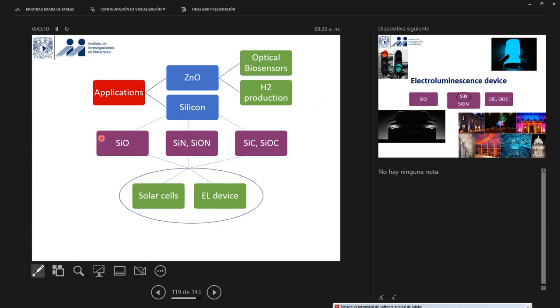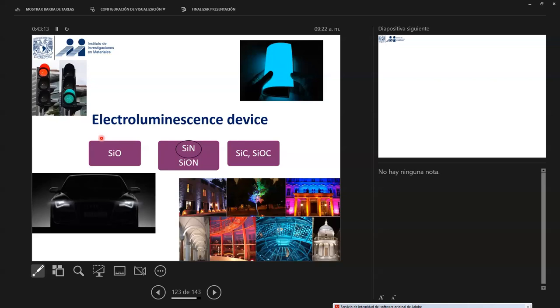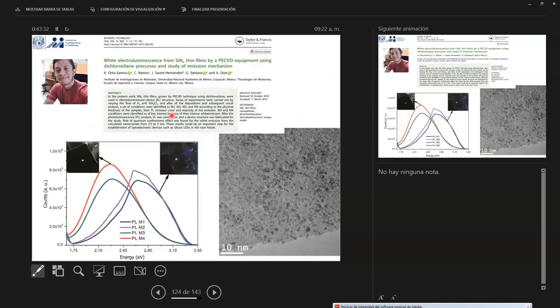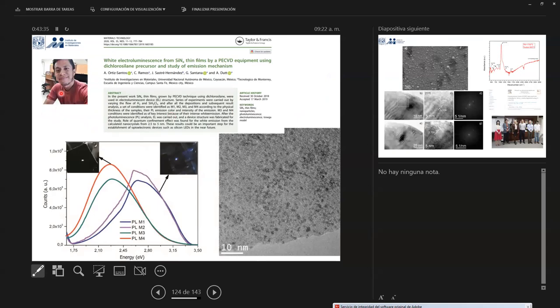Also, we are working on silicon structures. In this case, the aim is to use these silicon structures in different applications like electroluminescence. We can see some of the practical applications we have in cars, in ovens, in airports, and also in biological sensing activities. Silicon is quite novel actually. So that's what we are trying to do now. This was one of the first works published by Dr. Asayan. In this case, he developed two different kinds of electroluminescent structures, controlling the size of nanoparticles of silicon in a matrix. And you can see here, by controlling the size and density, he can control the band gap emission of these materials.